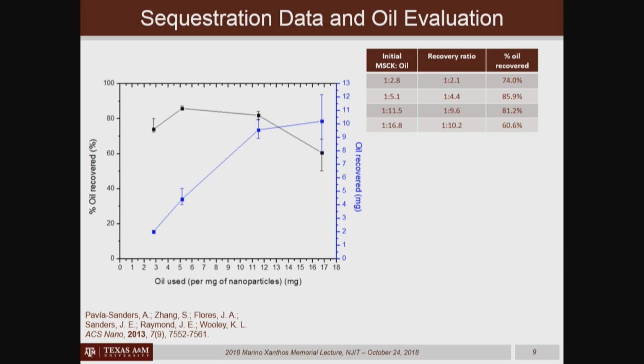And you can see that in all of these cases, she's able to collect about 80% of the crude oil until she exceeds up here about 16.8 milligrams of crude oil per milligram of particles. And then it drops to maybe about a 55 to 60% recovery. But at that point, she's recovering 10 milligrams of crude oil per milligram of particle. So this was a remarkable finding that they could take up 10 times their mass in crude oil.